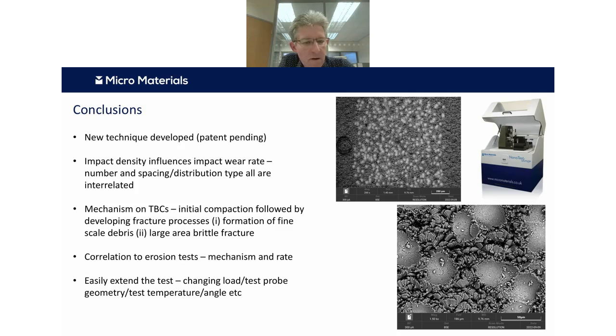So to sum up, hopefully I've given you a reasonable amount of information about our new test technique and some of the areas that we've applied it to so far. It's been very successful in that. And we're able to clearly show for all the materials we looked at that the impact density influenced the rate of impact wear or erosion, and effectively that the number of impacts and their spacing and distribution type were all interrelated. So that they all correlate together to give you an overall wear rate.